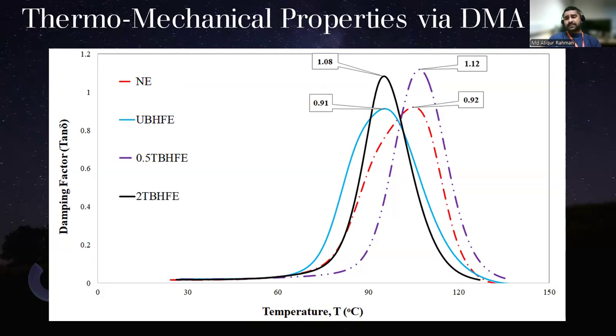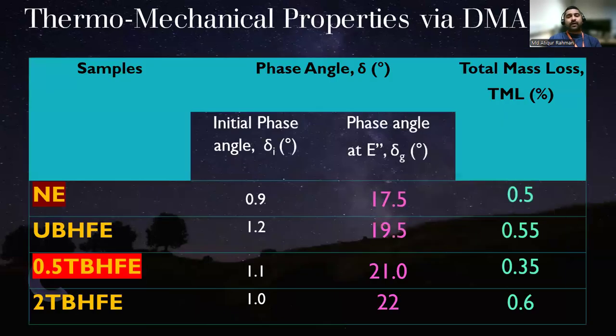So with this, that means this material can be used for structural analysis where the damping factor, the vibration, the impact factor is a necessary or critical property. Let's see some other properties which we found through this research work, which is the phase angle. After applying load, if the change of phase angle is 0 degree, that means the material is absolutely or completely elastic. If it is 90 degree, the material is completely plastic. In between, that is termed viscoelastic, which we actually look into.